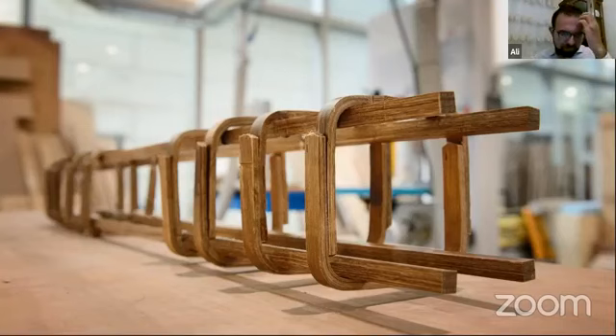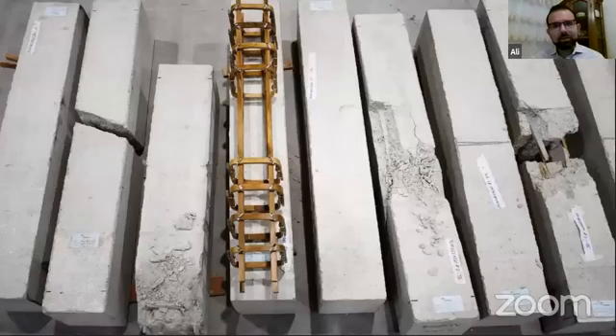Some of the testing that we have done, of course, we followed ACI FRP standards for designing the beams. We wanted to see where the shear failure happens, where the tensile failure happens, where the compressive failure happens in concrete. But most likely we wanted to have the tensile failure in the reinforcement, in our bamboo composite reinforcement. The results were quite promising. We published a paper on it. Even my thesis is also available at the ETH library, where I have explained all these calculations in very, very much detail.